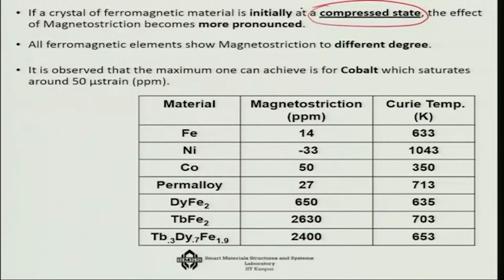All ferromagnetic elements show magnetostriction to different degrees, but all of them show it. It is observed that out of the general ferromagnetic materials, it is cobalt which shows the maximum magnetostriction, about 50 micron strain, where it saturates. Now, you may see that there are some materials which show negative magnetostriction. If positive magnetostriction means expansion, then negative magnetostriction is one of the rarer cases, where by using magnetic field you can even contract the system.